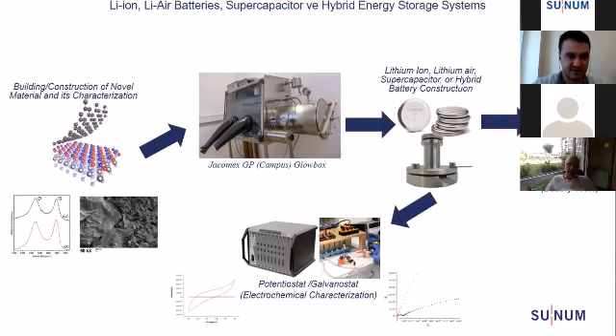In our studies, first, nanomaterials are produced or functionalized. And after successful characterization with Raman spectroscopy, for example, or sometimes scanning electron microscope, and sometimes equipped with focused ion beam technology, battery prototypes are prepared in a glove box. If the type of the battery is suitable, batteries can also be prepared outside of the glove box. And then cyclic charge and discharge tests are carried out with cycling instruments. On the other side, several other parameters can be obtained with the potentiostat galvanostat, as I said before, like cyclic voltammetry, electrochemical impedance spectroscopy, and something like this.